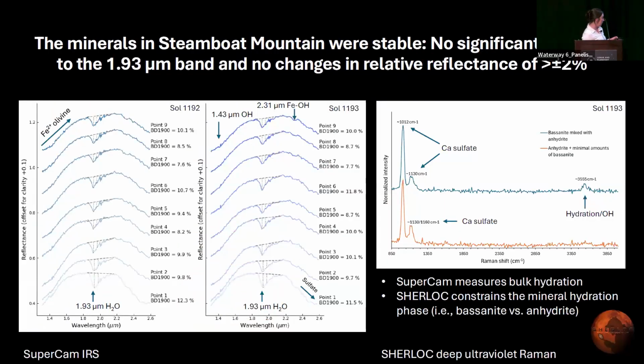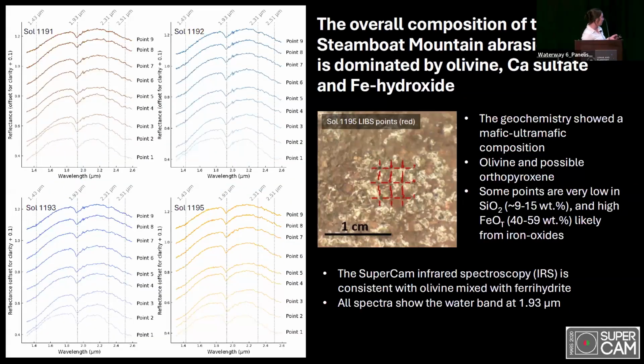So we can clearly see that there is a 1.9 band, a 1.93 band for the SuperCam data. And we did these observations on sols 1191, 1192, 1193, skipped 1194 and went into 1195. But the overall mineralogy using the SuperCam techniques of the Raman and the LIBS tells us that there is olivine present. We see that the reddish-brown matrix could be indicative of ferrihydrite. And in fact, this spectra does show a spectral signature consistent with olivine mixed with ferrihydrite.